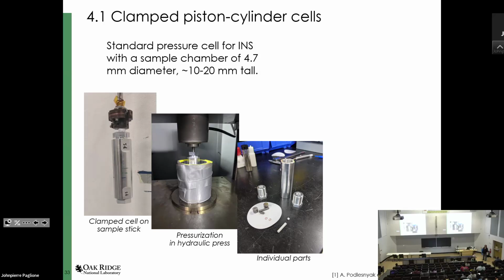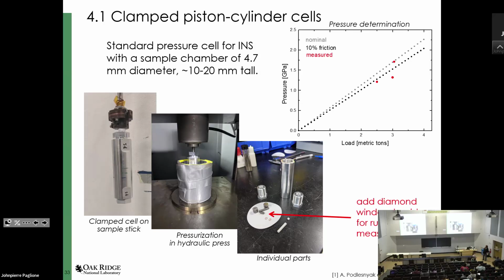Now, one thing that is tricky with these cells is determining the pressure because you don't have optical access. So that's something we started doing recently at Oak Ridge. We modified one of these pistons with a diamond window at the end so that you can get in a laser, which lets you measure the pressure with ruby fluorescence. I believe Adam will tell you later all about ruby fluorescence. Typically you would use a so-called pressure load curve as a guideline. You calculate the nominal pressure, pressure is force over area. That is the gray curve. Then you would assume that you lose some pressure to friction, say 10%. This is what you would assume as the pressure on your sample.